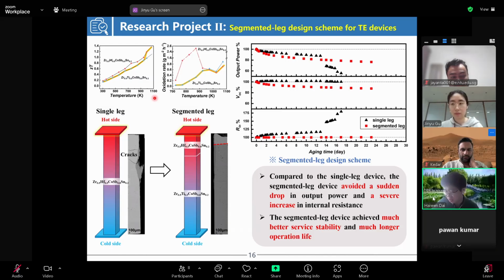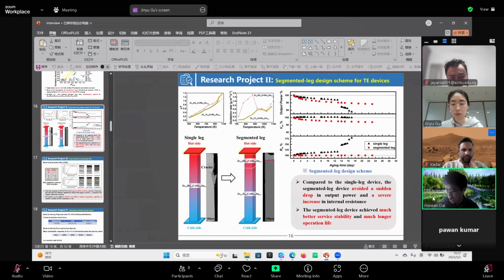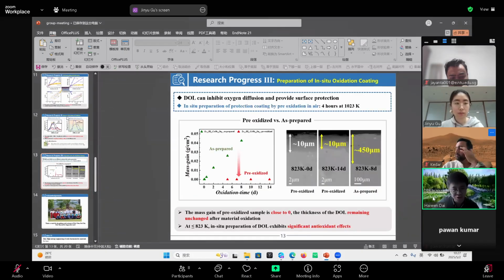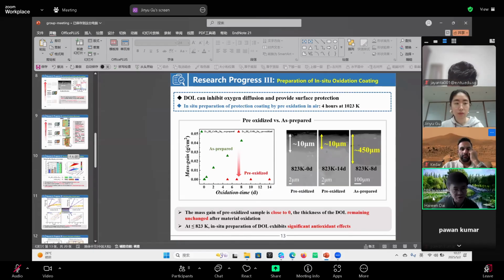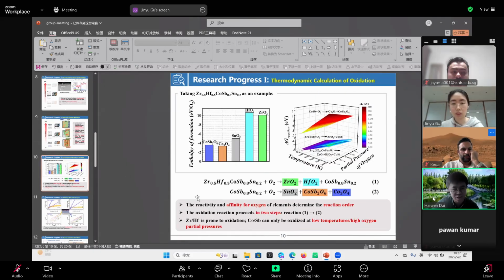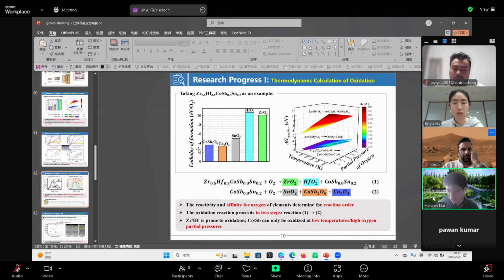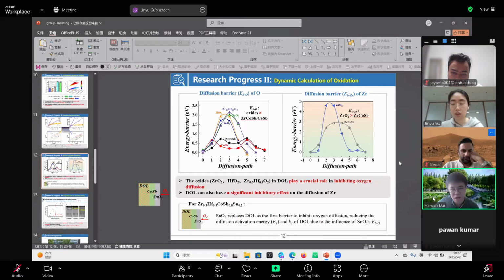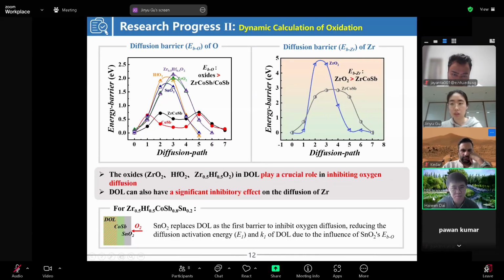And I had a question on the very basic. So I see your simulations. You have been using the reaction energies from the half-Heusler alloys to oxide, the delta G, as a thermodynamic metric to measure the easiness of the reaction. And you have also used the diffusion activation barrier, which is a kinetic term. So could you please comment, how much can each of these contribute? Which one is more important here, the kinetic one or the thermodynamic one?